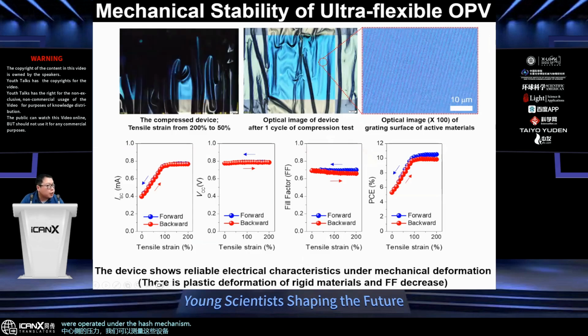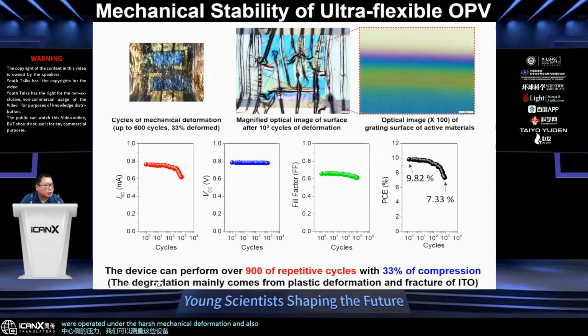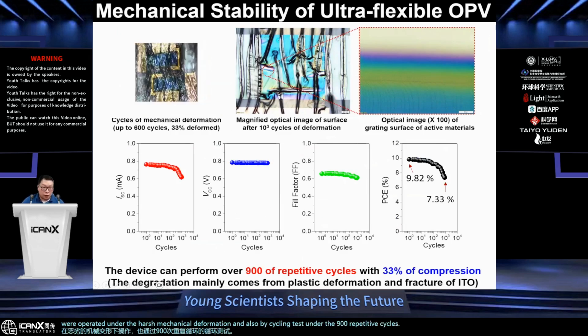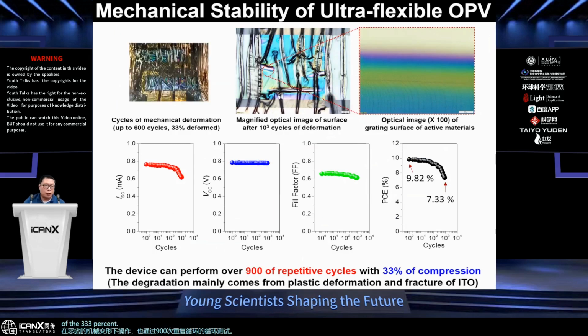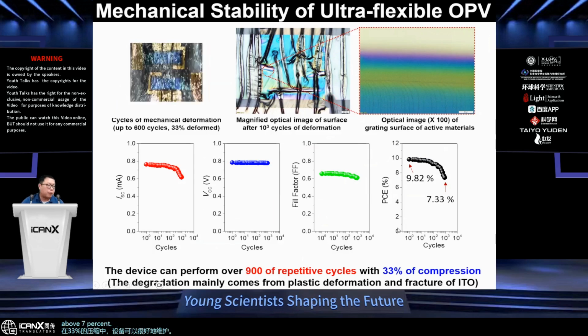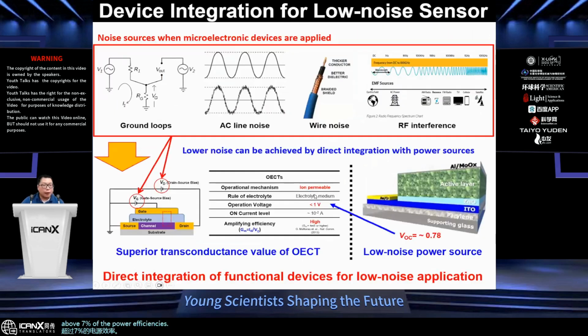So by applying the pressures to the center side, we could measure that the devices operated under harsh mechanical deformation. Also, by a cycling test of 900 repetitive cycles with 33% compression, the devices can be well maintained above 7% power efficiency. So as I told you, the power sources and their integration with the sensor is quite important when we try to measure the biological signals from the skin surfaces.